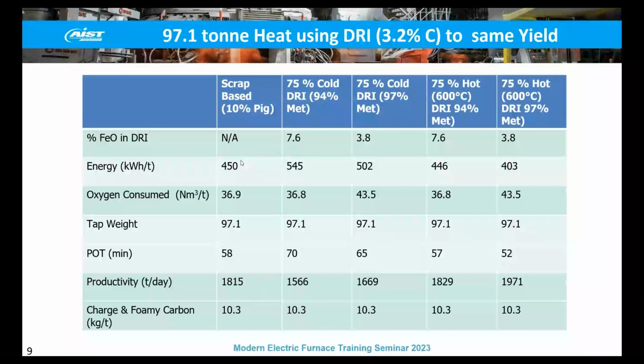So this is a chart showing a few different arrangements of scrap, cold DRI, hot DRI, and different metallizations of DRI. Using this as kind of the base of where historical electric arc furnaces might be operating, say 450 kilowatt hours per ton, you're looking at a 100-ton furnace, power-on time 58 minutes for this example, making 1,800 tons a day.